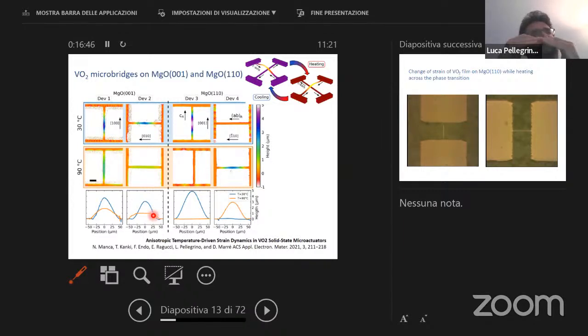So when you release from the substrate, they bend. But if you heat up above the transition temperature, you have this transition, of course, because you are changing, you have a contraction. You are changing the lattice parameters. Instead, if you are working with MgO 110 films, you have a very interesting behavior due to the anisotropy. We have the c-axis direction, and you heat up. You have the phase transition. You have a contraction, full contraction, and you have the bridge that is really changing the bending.